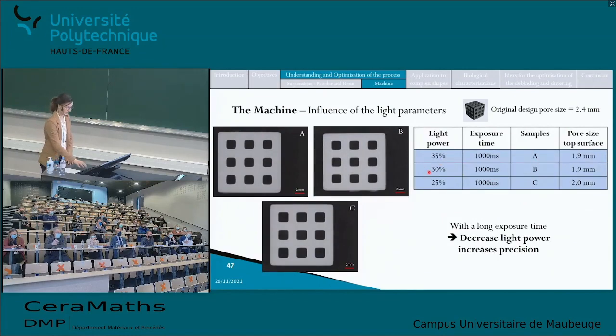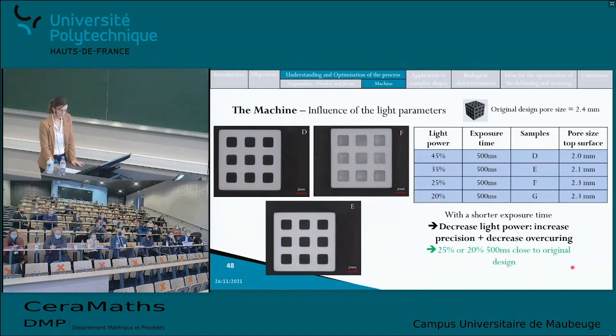So when I decreased both the light power and the exposure time, I finally managed to obtain samples F and G. So here, those were the ones with the pore size on the top surface that were closer to the original 3D design.